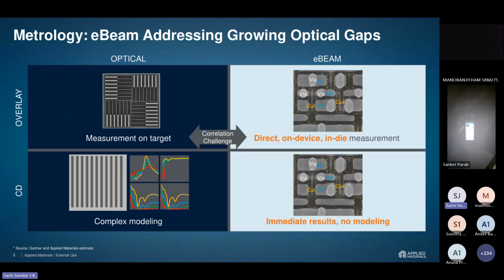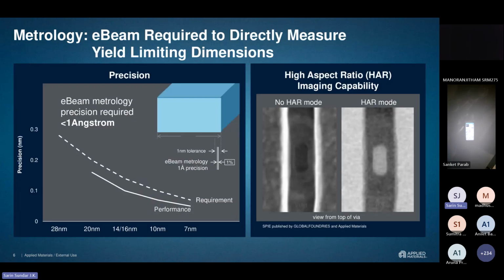And you can see the optical gaps. On the first, you see the overlay errors, because this is from layer to layer. Direct on-device or in-die measurement is done when they do overlays between the layers, and CD is on the particular layer. Okay? And basically, you use this to measure any yield limiting dimensions. For example, on the right-hand side, you have a high aspect ratio mode where the top of this is actually a via. Via means it's a hole, right?